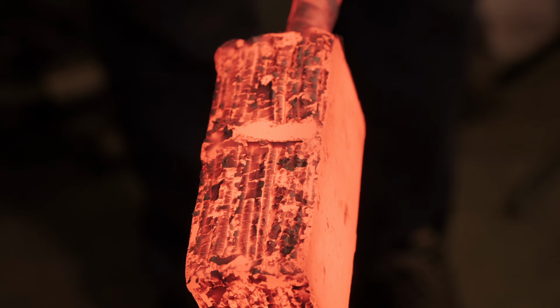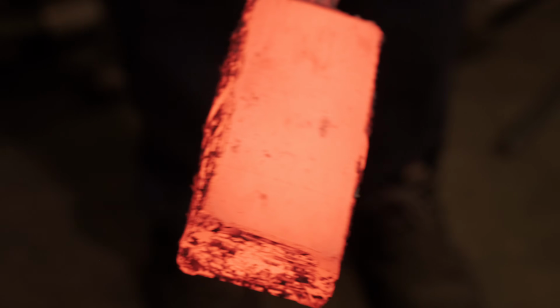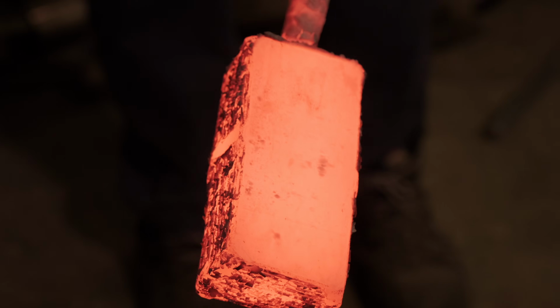With carbon steel, it's not too critical. If you do get a minimal amount of oxide forming on the surface, it actually dissolves into the metal during the forging process. It doesn't seem to cause any problem. It doesn't cause delamination problems. The oxygen diffuses through the metal and probably ends up on the outside, back in the atmosphere again. I'm not 100% sure on that one, but it doesn't create a problem.